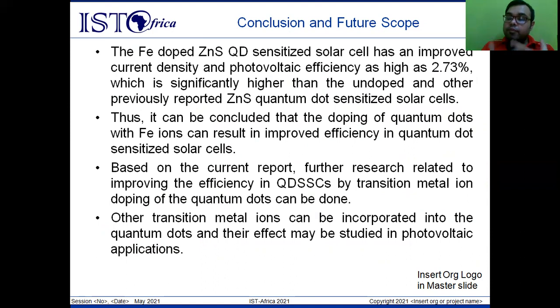Further research is possible based on our present work. For example, we can try different transition metal ions on zinc sulfide quantum dots. Here we have used iron. One can use copper or manganese on zinc sulfide quantum dots and see the result of increased efficiency. How much is the increase? Or one can use different quantum dots using the same dopant. That is, one can dope iron ion into different quantum dot based solar cells.